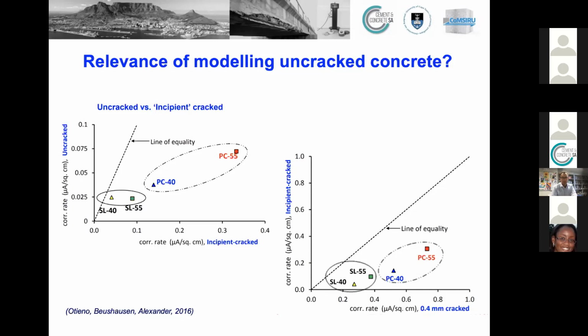And you can see that even if the concrete has a hairline crack, which means you can't even measure the width, corrosion rates are much higher compared to uncracked concrete. On the bottom right, we are comparing hairline cracks to cracks of 0.4 millimeters crack width. So what these graphs are showing is that even though we measure penetrability on uncracked samples and use that in our service life models, in situ we can very often expect much higher corrosion rates, because our concrete very often is cracked from shrinkage or structural cracks and so on. This once again speaks to the approaches we use for service life modeling not being very reliable or relevant.